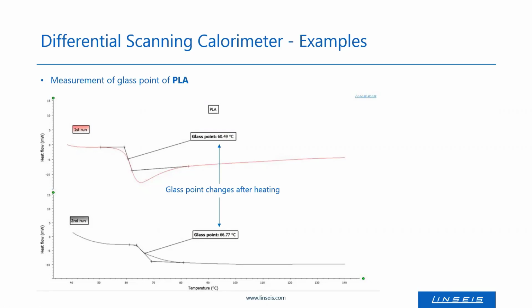So this glass point can shift in different directions, so to say, depending on the heating rate and also on the cooling rate. This is also a crucial parameter because depending on the heating cycle and the cooling cycle, the mechanical properties of the then printed material can be influenced.